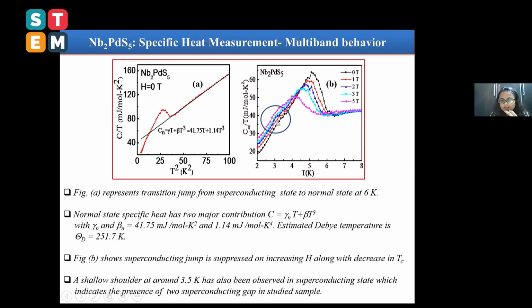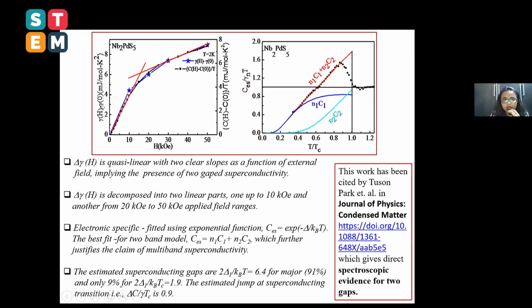Here you can see that a shallow shoulder at 3.5 Kelvin has been observed in the superconducting region, which indicates two superconducting gaps, as previously studied in the case of MgB2 superconductors. And this is the gamma H versus H curve. Here you can see that this is quasi-linear with a clear slope change: one region is from 0 to 10 kilo oersted, and another region is from 20 to 50 kilo oersted.